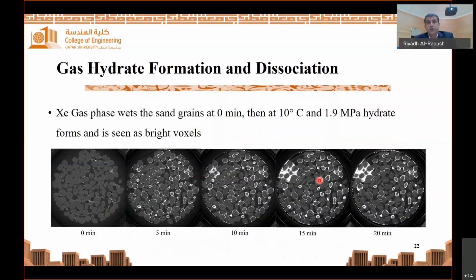This is another experiment where we use computed tomography. We looked at the dynamics of hydrate formation and dissociation in porous media. We used xenon gas, which was injected into a fully saturated sediment at a temperature of 10 degrees centigrade and a pressure of 1.9 megapascal. These are cross sections from 3D images where the inside diameter, again, is 1 centimeter. These images show how we can capture the development of hydrate as a function of time. You can see that the gray scale here is the porous media or the sand phase, and the white here is the hydrate formation as a function of time.